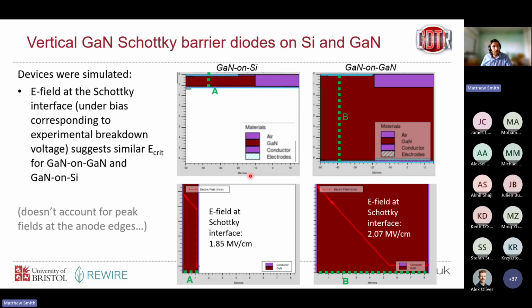And again, it tends to suggest that the more important limitation for GaN on silicon is thickness, how thick we can grow these layers. Although, of course, earlier we did see that there is an effect of dislocations, but if we can achieve relatively high quality material, if we can grow thick material, then you should be able to achieve relatively high breakdown voltage in vertical GaN on silicon devices.